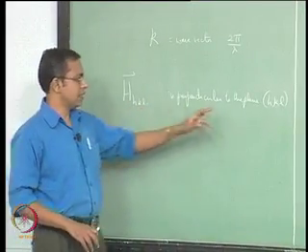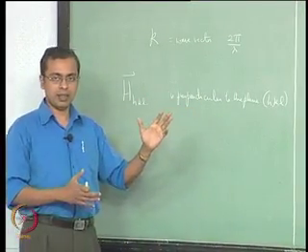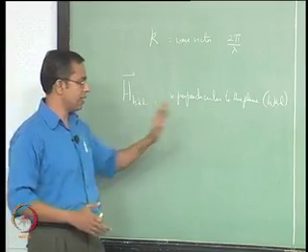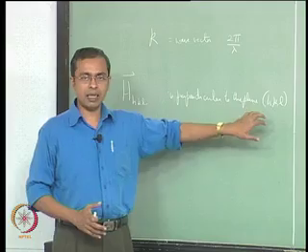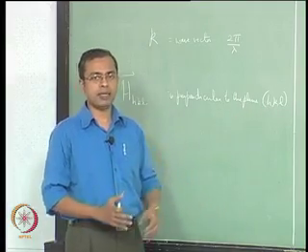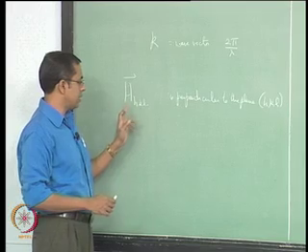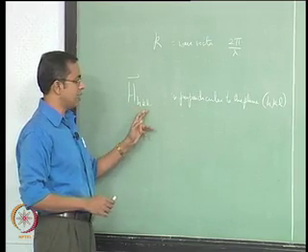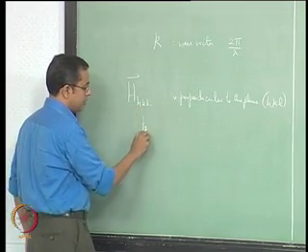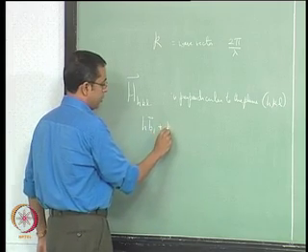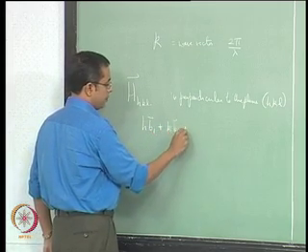And since the unit vectors in these two spaces have been defined, or at least the reciprocal lattice vectors have been defined with respect to the real lattice vectors in a specific manner, that is why we end up finding that this relationship holds true, that the reciprocal lattice vector hkl, which would then be h b1 plus k b2 plus l b3.